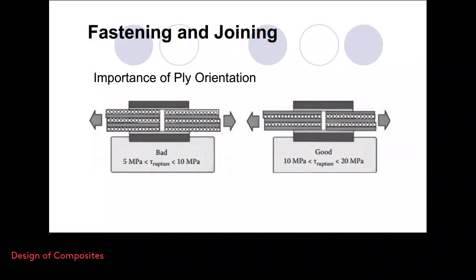Okay, so let's see the orientation of the fibers in such a circular shaft. So the first design, even though the rupture stress is between 5 megapascals and 10 megapascals, when you apply such a bonding, and if you put the ply which has a fiber orientation perpendicular to the loading on the outer surfaces, certainly you may possibly have matrix fiber debonding, and you see a failure in the matrix.